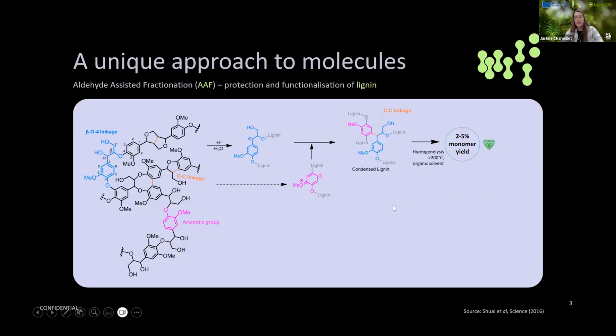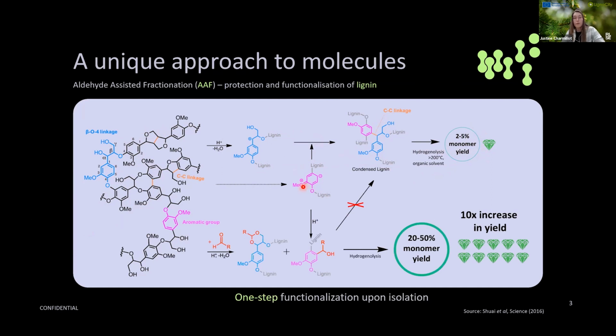So more on the technical side, how does it work? We have here the lignin in the biomass, and typically, in a typical process under harsh conditions, C-C linkages might form, and those are really difficult to break when we want to go to the monomers that are high value molecules. We typically get really low yield, and that's the idea of Bloom: to use an aldehyde that will incorporate into the lignin structure and those beta-O4 linkages, for example, and will then prevent this condensation from happening. And then when we try to do a hydrogenolysis to depolymerize it, we typically get a 10-fold increase in yield.